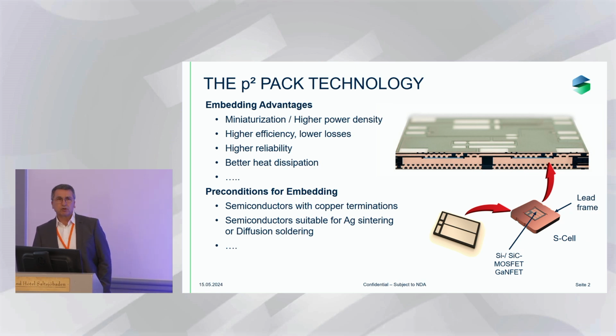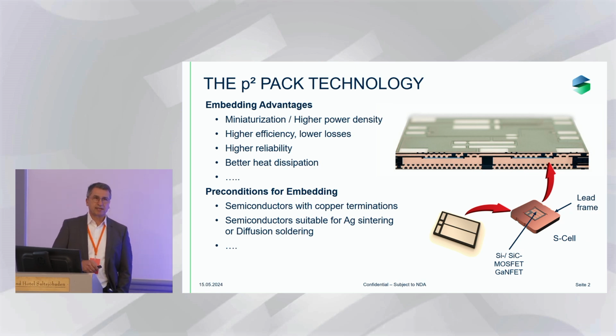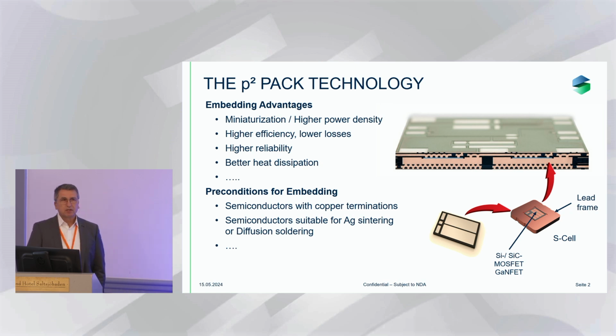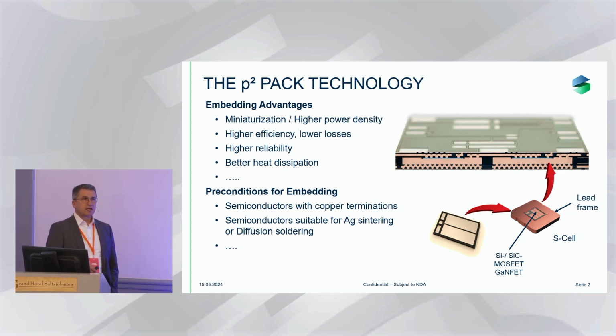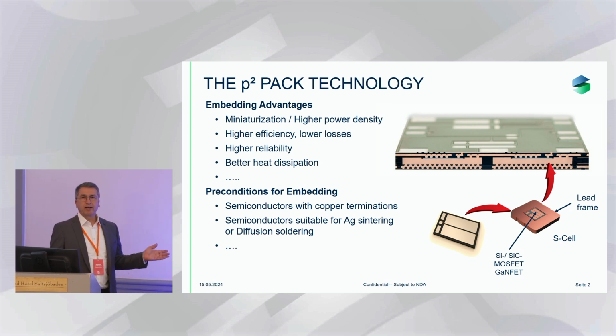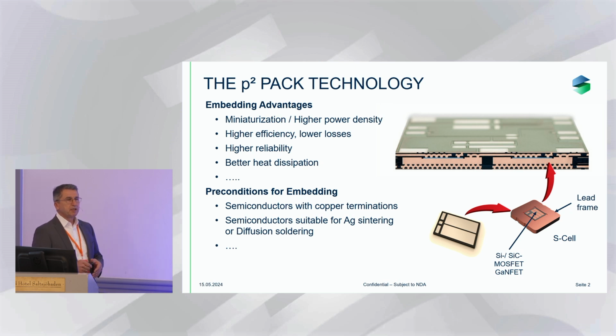For power electronic components, one of the most stressful tests is the power cycling test. And if we do that, normal power modules are tested at a delta T of 80 kelvins. If you do this with such a P-square pack, you will test it forever, because you don't see any failure. We tested more than 2 million cycles and we had to stop the tests because we didn't see anything. We had to increase the delta T during the testing to provoke any failures.